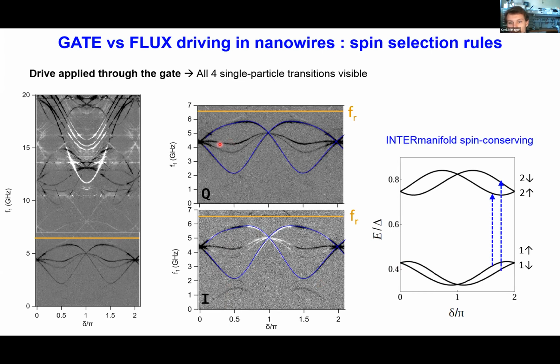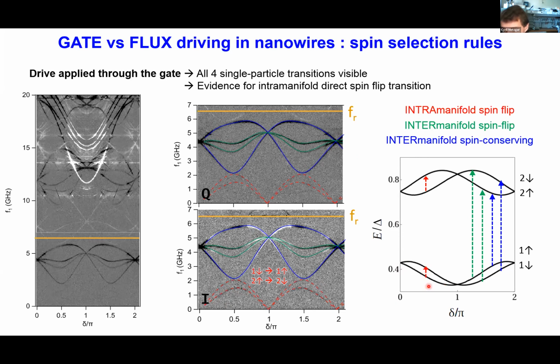So you can see here intermanifold spin conserving transitions in blue, which correspond to this process here, and also the inner lines, which correspond to spin flip transitions. And it also came to us as a big surprise that we actually were able to see another kind of transition here that corresponds to spin flip transitions within a manifold. So this was only possible to observe because we were driving through gate. And I think the next talk by Yale will deal more specifically with this kind of transition and the possibility of making an Andreev spin qubit.